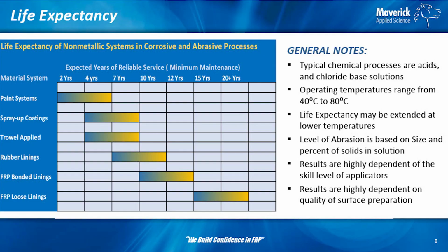So the rubber lining, 10, 12 years, like I said, we start seeing issues. Something between 5 and 7 is generally where it starts. It's been our experience. I mean, we hear people that say, "Oh, we've got linings for 20 years or something." That can happen if it's in a mild service. If you got a great vendor and everything kind of lines up, it can happen. Okay. Dale talked about chlorine headers and 40 years service. We don't see that. I'd like to figure out what they're doing, because we would share that. But it can happen, but there are a lot of factors that have to line up for those things to happen.